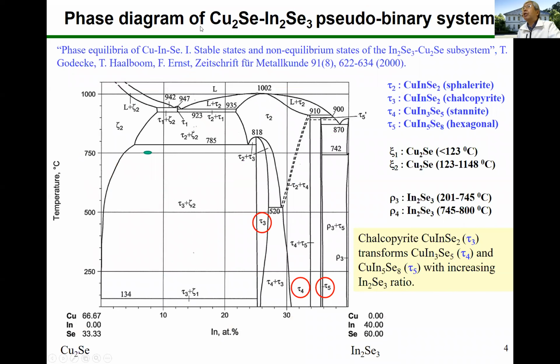This is the phase diagram of the Cu2Se-In2Se3 pseudo-binary system. Chalcopyrite copper indium diselenide, tau-3, transforms to CuIn3Se5, tau-4, and CuIn5Se8 with increasing In2Se3 ratio.